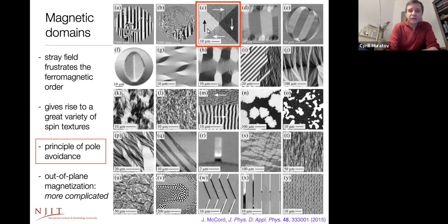This is also an example of a pattern that is recurrent in ferromagnetic materials. This is called a pattern of magnetic domains. What these patterns typically consist of are large regions of space in which the magnetization is essentially constant, separated by narrow transition regions where the magnetization changes abruptly from one constant value to the other. These are what is called the magnetic domain walls, and these are magnetic domains. My talk is going to be about trying to understand the domain walls separating the magnetic domains.